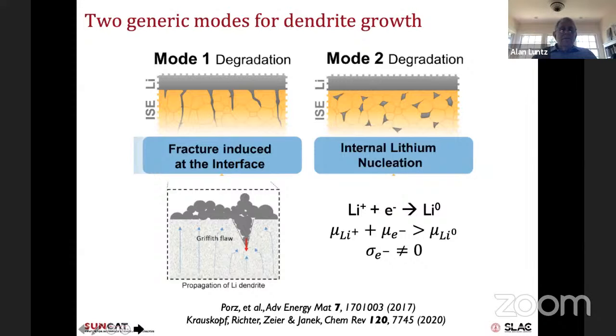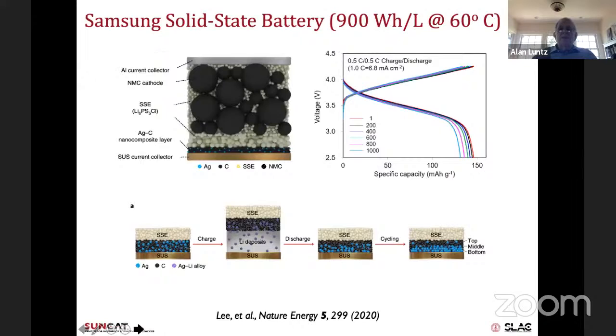Okay, so let me just show you one example of what I think is probably the best solid state battery that exists right now in the laboratory, at least in the published literature. This was an anode-free design where they took state-of-the-art nickel-rich NMC cathode material, coated it with lithium zirconium oxide to isolate it from the solid state electrolyte, which was a chlorinated sulfide, this particular material. The thing that was different is they had no lithium down here. They had a silver carbon composite layer a few microns thick.